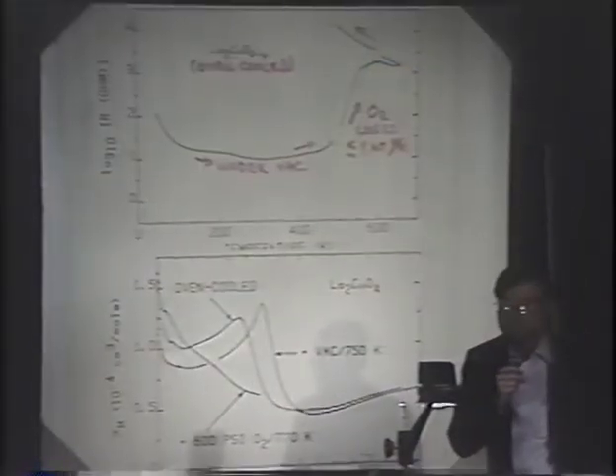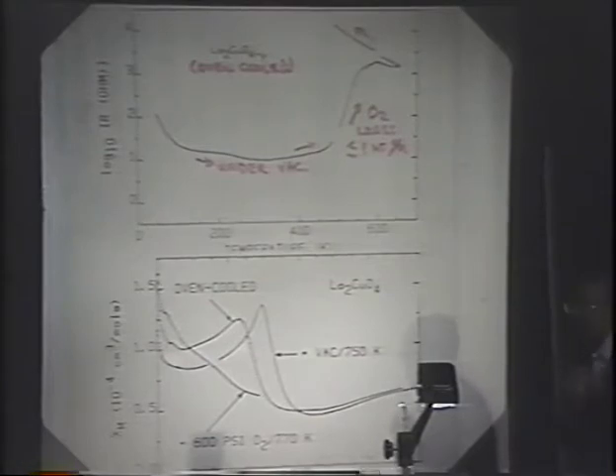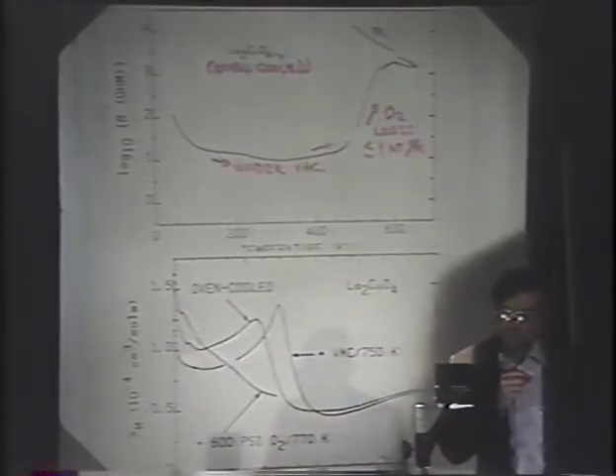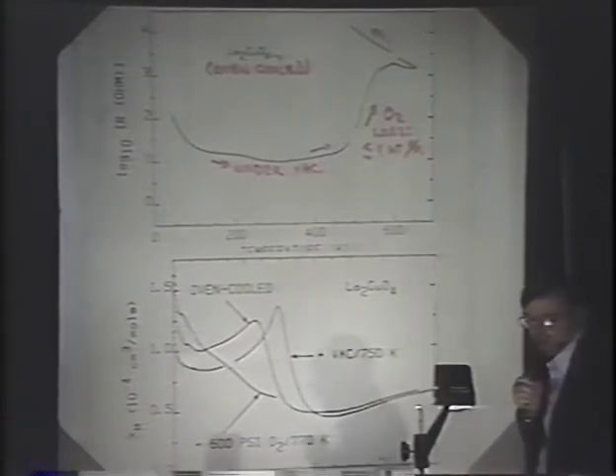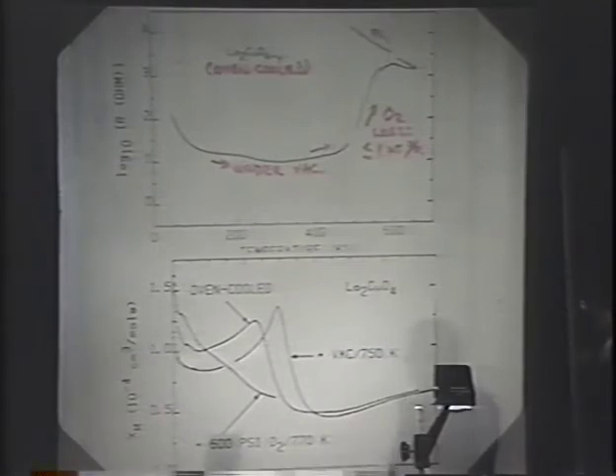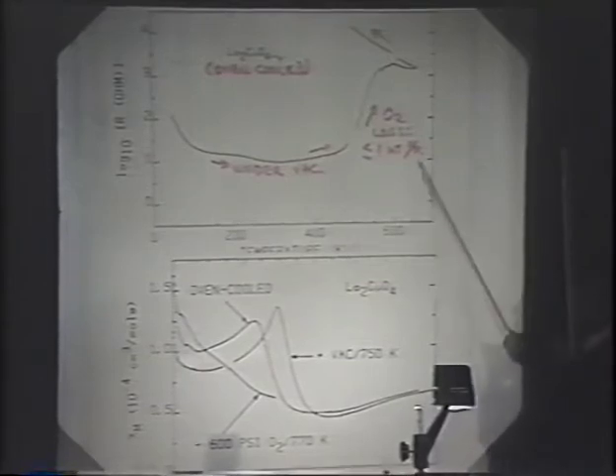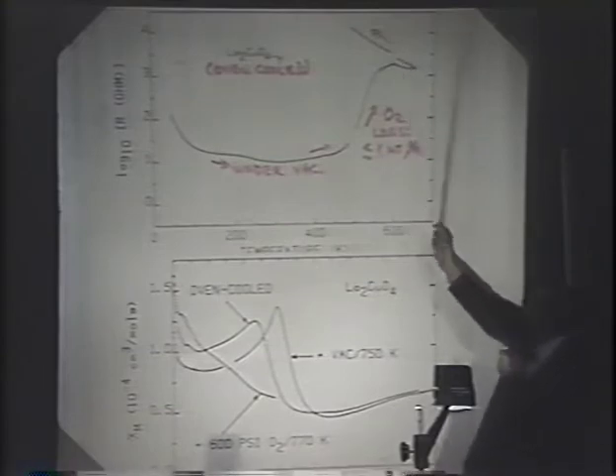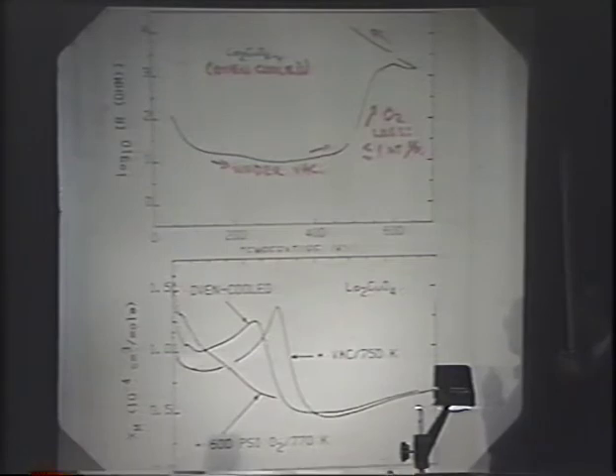Plotted at the top, just to remind you, is the log of the resistance versus temperature for the pure lanthanum end member. We took an oven-cooled sample, which has some nominal stoichiometry of oxygen in it, and heated it up to 700 Kelvin. We know from gravimetric measurements that above about 500 Kelvin, it loses oxygen. What we see here is an irreversible change to a state which is much more resistive. The amount of oxygen lost is roughly on the order of a tenth of an atomic percent.